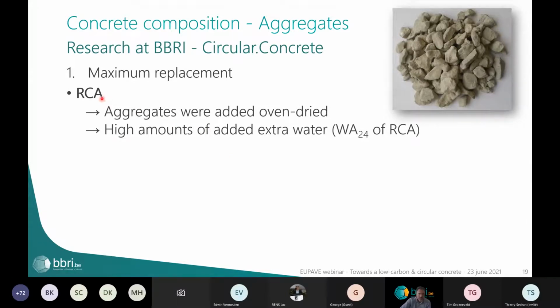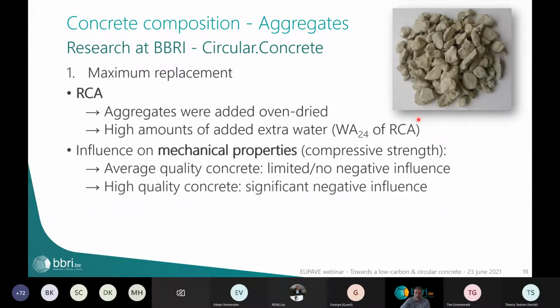Also, very important is that we added the recycled concrete aggregates in oven-dried state, and then we added extra water to take into account the water absorption of these aggregates, which meant in fact that high amounts needed to be added to take into account the water absorption of the recycled aggregates. Of course, the value we used to calculate this was the water absorption after 24 hours, and we know that when we mix dry aggregates in concrete, they will not absorb 100% of their water absorption after 24 hours. So there is added water that is not going to be absorbed by the aggregates. And of course, we looked at the influence on the mechanical properties, mainly the compressive strength of concrete.